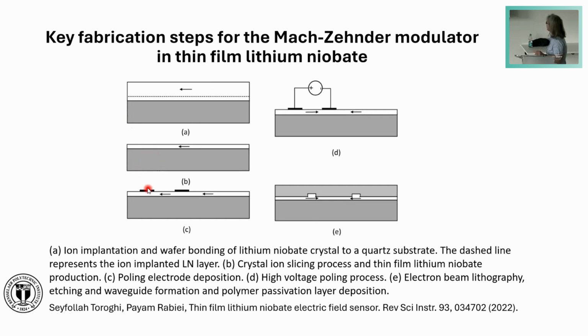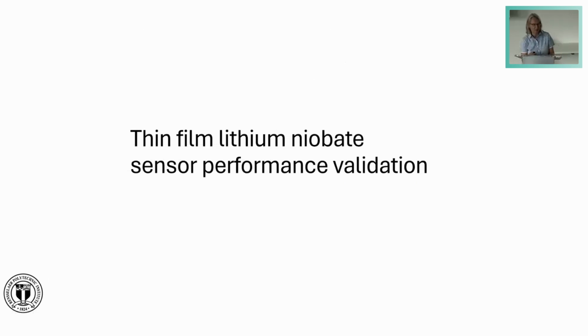Then for the poling of the lithium niobate, two metal electrodes are applied to the thin film, and then an electrical voltage is applied, and in one area the polarization is reversed. And then in the next step, using electron beam lithography, the waveguides are defined, and the other structures like the multimode interference couplers and the gratings for coupling, and then the device is ready, and then there's a passivation layer on top.